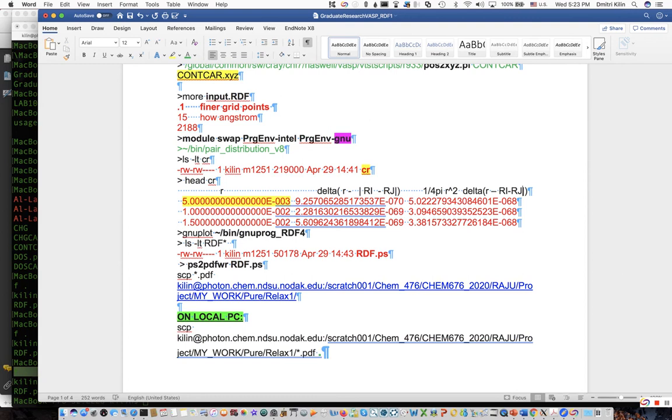This script does not take into account periodic conditions. So if the argument is bigger than half of the cell, the results do not make sense. One always needs to select an X range smaller than half of the cell, then it will make sense.